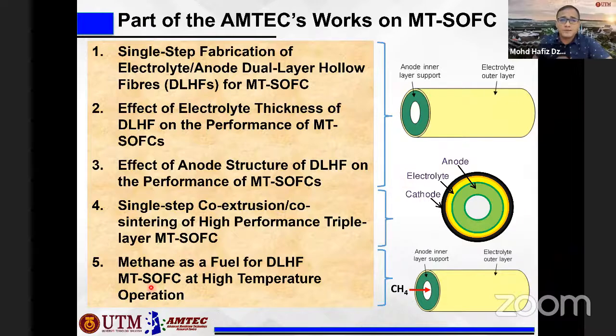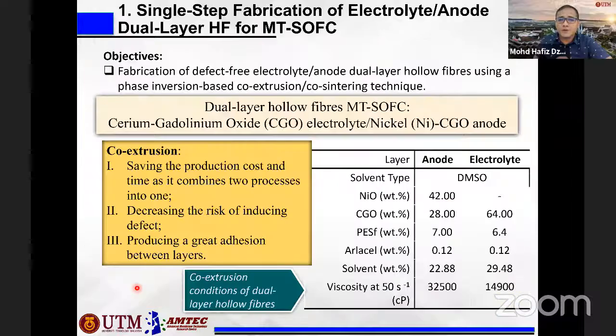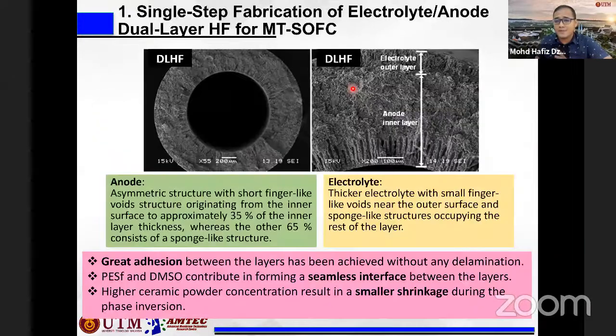So for the first phase, the objective is to produce a defect-free dual layer hollow fiber membrane, which consists of the electrolyte and anode. And these are the fixed parameters that we use for the anode and electrolyte. In terms of the structure, using the dual layer has advantages because it can produce very great adhesion between the layers without any delamination.